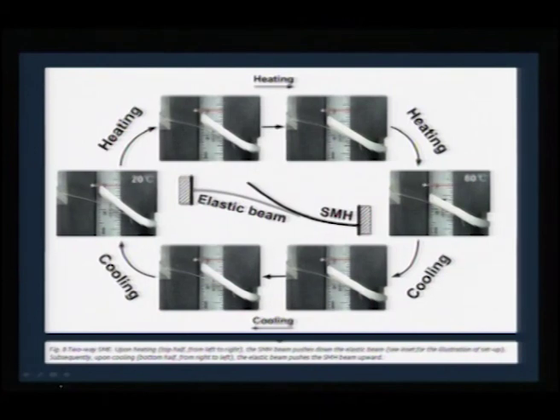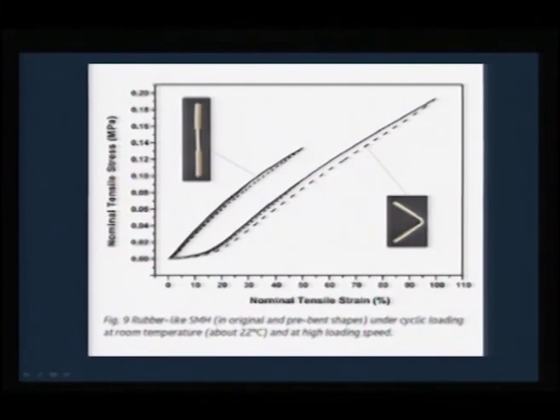This is another demonstration of how a hybrid polymer can be used. This is a shape memory hybrid polymer, and now we can start heating this polymer, and you can see here as you heat the cycle, slowly there is bending and it is actually touching an elastic beam. This is the elastic beam, this is a shape memory hybrid. Now from here it almost comes in full contact with the elastic beam here at 60 degrees C, and on cooling again you can see that it reverts back to its original position. So, this sort of thing can be used for several applications, because you can reverse and bend the shape by changing the temperature. Here again you can see the way the cyclic loading occurs when you use a shape memory hybrid. You can try to bend it any way and you can try to again retain back the same shape. This is a rubber like stuff.